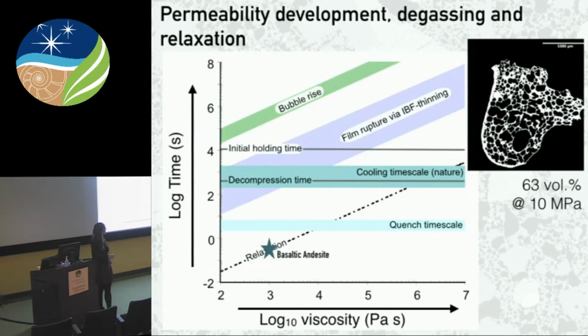The relaxation timescale is the amount of time it takes for a bubble to respond. What we think is happening is that these samples are essentially foaming up, developing permeability, and then that causes a decrease in internal bubble pressure, which causes the bubbles to shrink. And this could result in why we're seeing lower vesicularities for a given quench pressure.